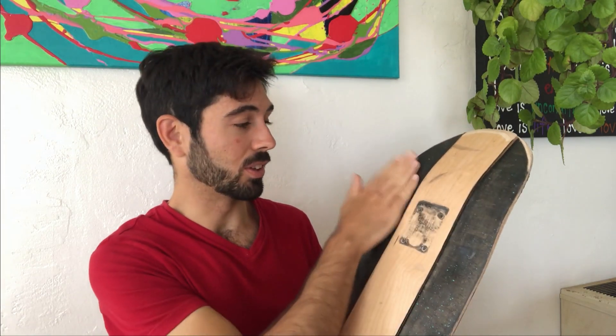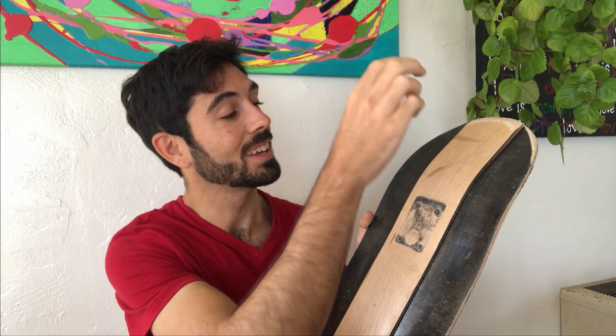The reason for that is I didn't use enough glue in the layup, and I kind of knew that going in. I tried something I normally don't do — just putting glue on one side of the veneer instead of both sides. Normally I glue both sides and put those glued faces against each other. With this board I didn't want to do that because I wanted to keep the surface smooth since it would be exposed, and I didn't want to sand off extra glue. So I only put glue on the centerpiece, and I didn't put enough on.